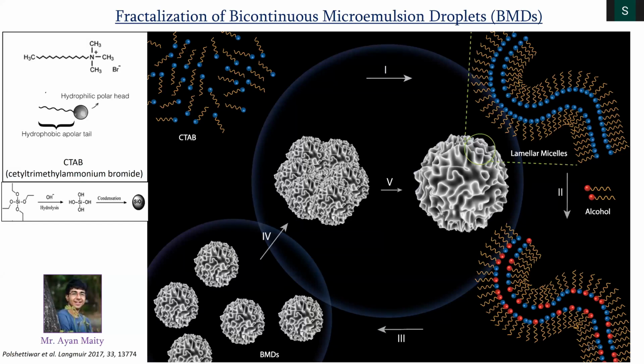The question that we ask in our lab is why these spheres are dendritic fibers. Why not a solid sphere or a hollow sphere or some other shape, other morphology? Why this particular? And that's the question that we ask in our lab. The formation mechanism of this material, and this is synthesized using the technique called the templated synthesis, where you use this type of organic molecule as a template. You can see there is a quaternary nitrogen, which is a polar head shown as a blue ball, and you have this CH2 up to 16 times, which is a hydrophobic tail.